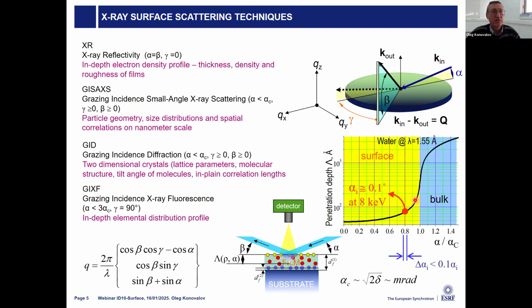Now, first, a few words about the surface scattering techniques: how it works in general and what we can learn out of that. If we want to discriminate the scattering between the surface and the bulk, how do we do this so that we have the majority of the signal from the surface? For this, we use a very interesting feature of X-rays, that they have an index of refraction which is smaller than 1. It means that at small angles, below total reflection from the surface, the penetration of the X-rays in the material is very small. Then it can be controlled depending on the grazing angle.